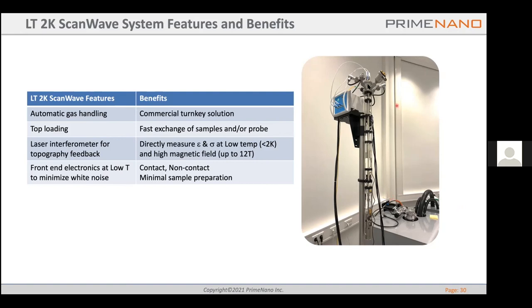It's a top loading system, which means you can just take the probe out to do quick sample exchange. It can directly measure conductivity and permittivity below 2 Kelvin, and it's also compatible with magnetic fields up to 12 Tesla. You can do contact measurement and non-contact measurement, and sample preparation is pretty straightforward.